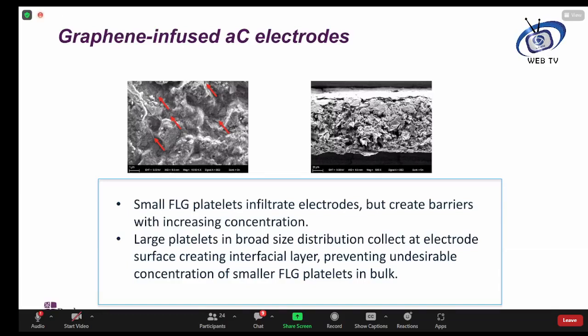And the reason why large platelets generally work as a broad size distribution is that we prevent too much accumulation of few layer graphene in the electrode material. So we prevent it from going from a situation where we have a beneficial concentration to blocking the pathways by which the ions can reach the surface of the activated carbon particles, and it forms a continuous backplane which reduces the contact resistance with any current collector that we use.